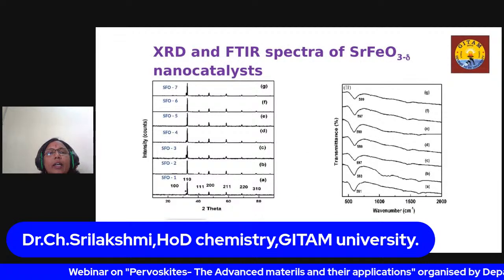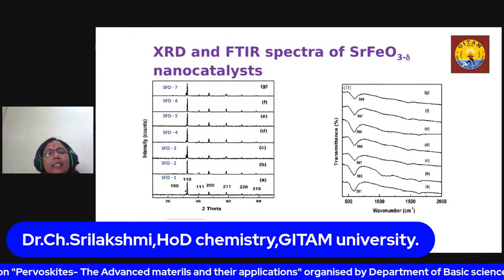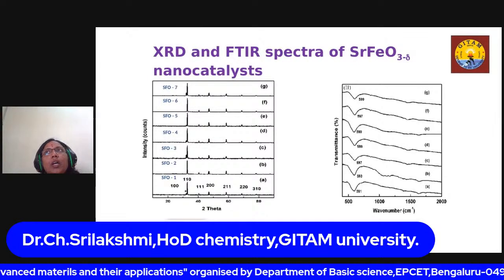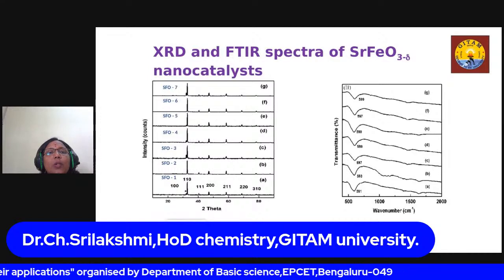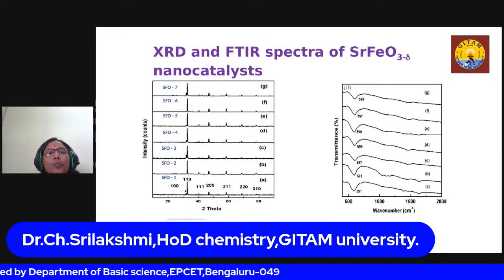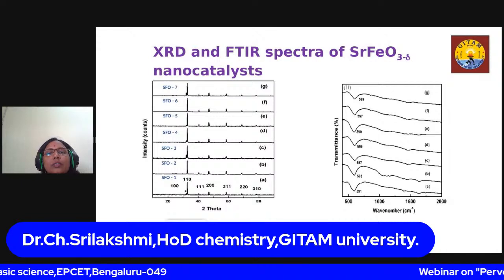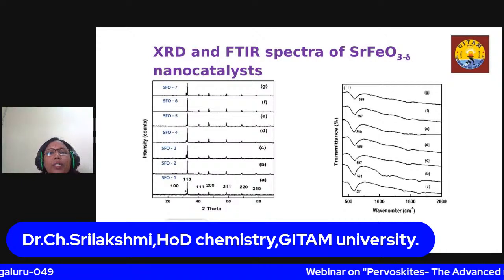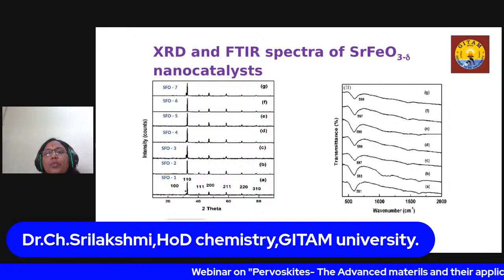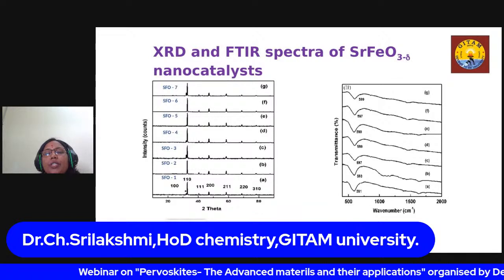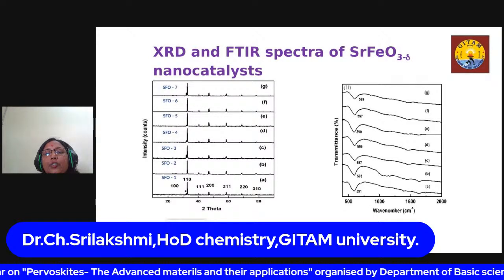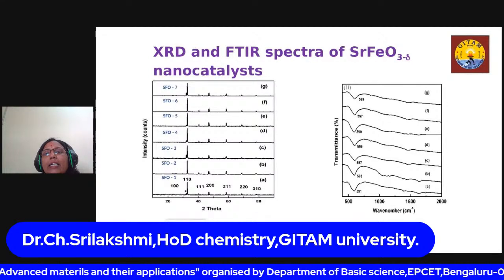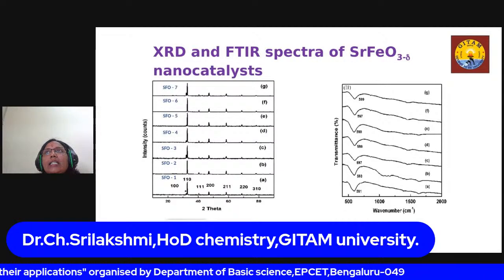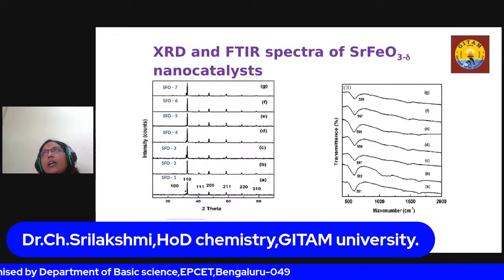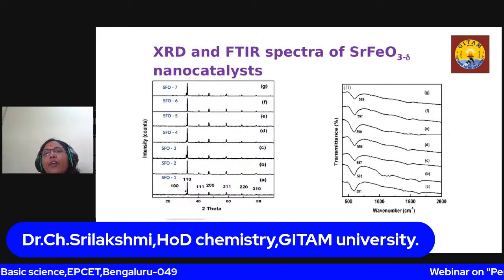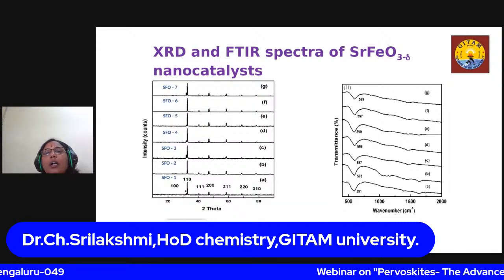Again, in the XRD, except for the second sample, which was synthesized using just oxalic acid, all the samples showed an impure phase, which is Sr4Fe6O13 or something like that. IR confirms that there are Fe-O stretchings, and there is a broad band containing a shoulder at 545. That indicates the strontium ferrite has a defective structure, SrFeO3 minus delta, it is not 3. So it is a defective perovskite, not the complete perovskite.